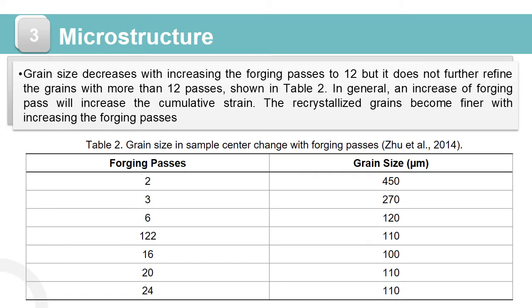Grain size changes with the increase of the forging pass, as shown in figure 3, presented by Yu et al. It shows that the size of grain in the center of the sample decreased with increasing the forging pass to 12, but it doesn't further refine the grain with more than 12 pass, shown in table 2. In general, an increase of forging pass will increase the cumulative strain. The recrystallized grain becomes finer with increasing the forging pass.